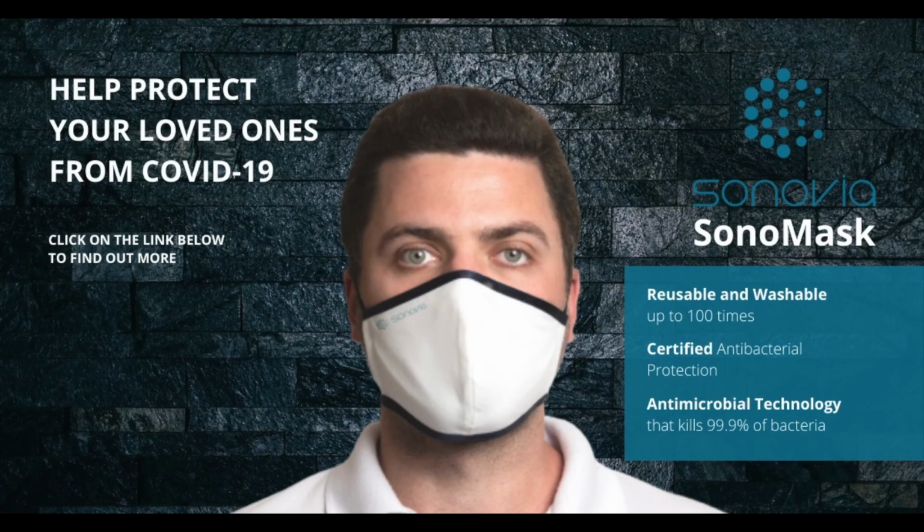So this was the movement that started, and then we submitted tests and applications to provide real validation for the zinc oxide formulations. And we were pleased to announce that the fabric was submitted to an EU authorized lab, and it showed that there was a 99.87% reduction in envelope viruses when using an analog of the coronavirus. So this was a virus that had been altered to express similar proteins to the coronavirus, and this really showed that the fabric had an antiviral basis. So we now had claims we can make, and after that, FDA applications are underway.